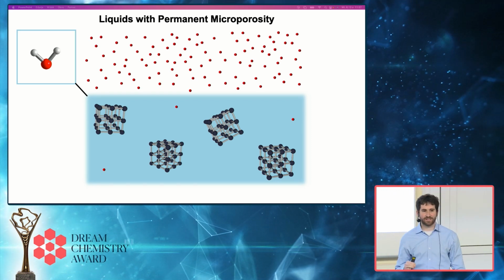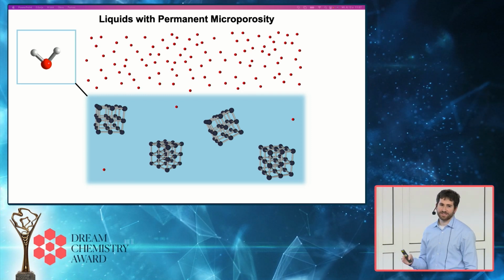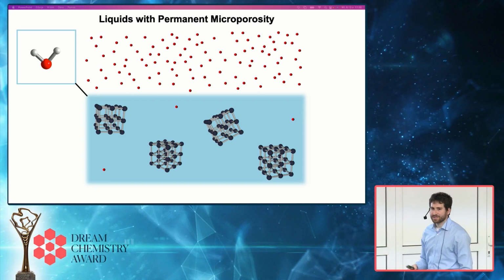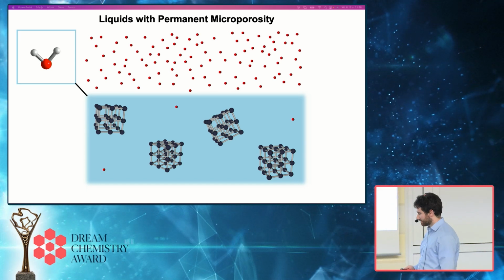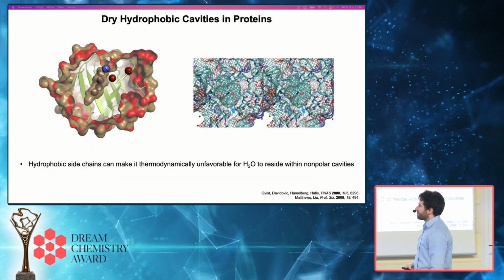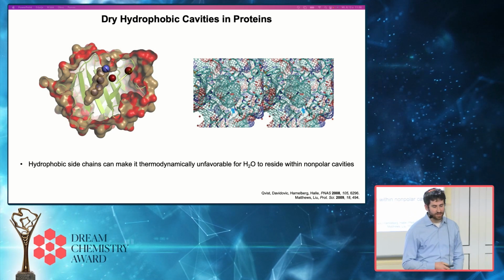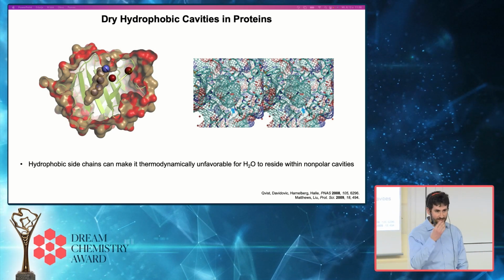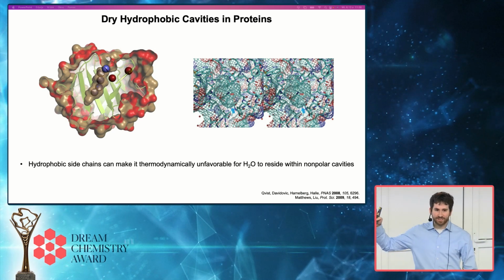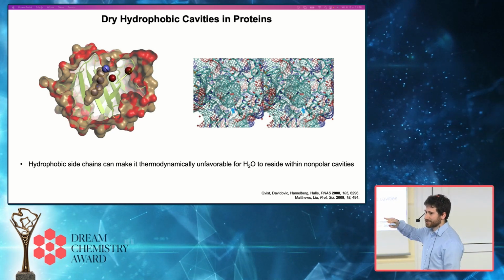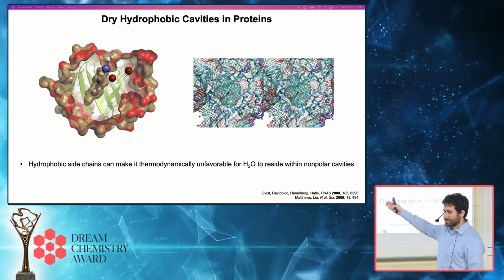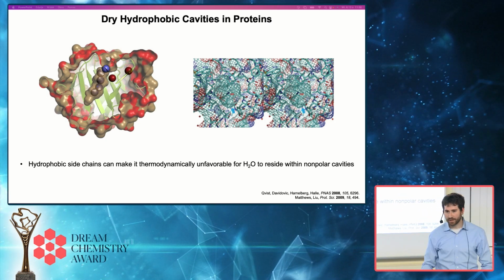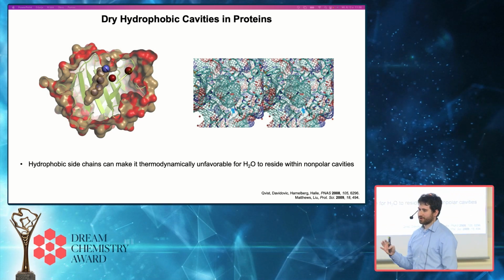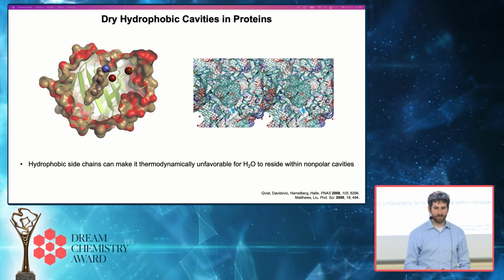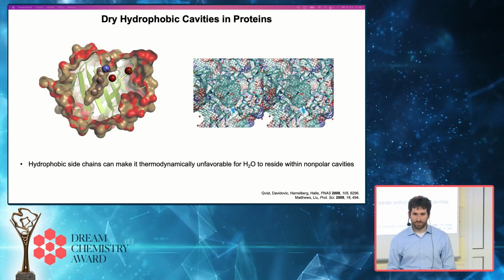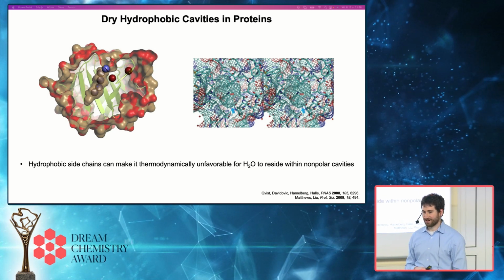And so we wanted to find a way to get around this and a way to preserve actually the porosity of a microporous material in water and see if we could leverage that for transporting gases effectively. And so we were inspired in part by two things, one from biology, and that's the fact that there's a lot of proteins that exist naturally that have really large cavities that are not closed. They're open to the aqueous environment, but the cavities themselves are actually dry. So water is accessible to the cavities, but water doesn't actually go inside the cavities because it's thermodynamically unfavorable for it to do so. This can be both enthalpically and entropically unfavorable.